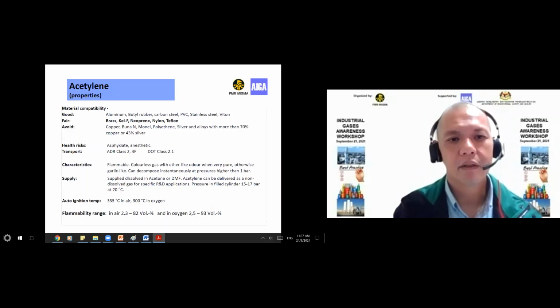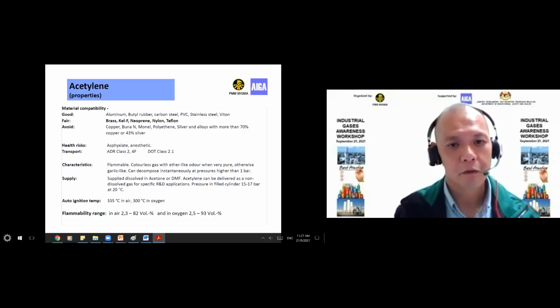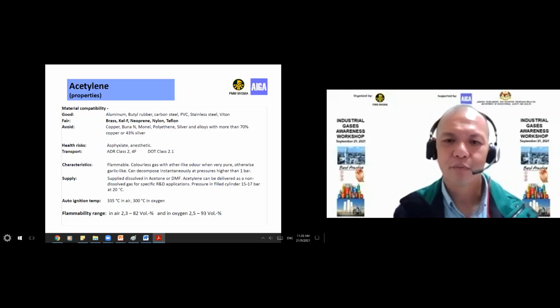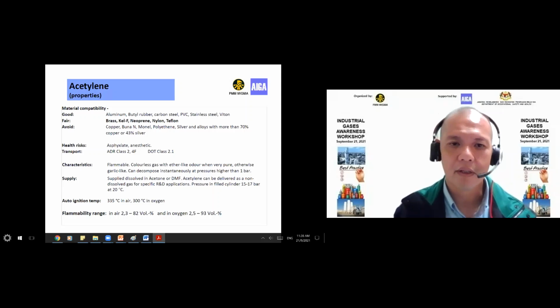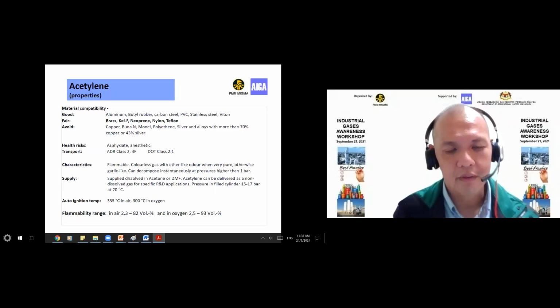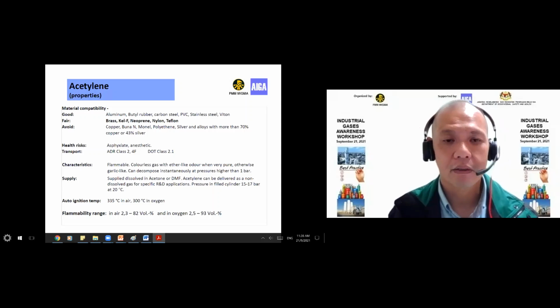Right, so here I want to share the material compatibility with acetylene. For acetylene, there are some good materials that are very compatible, like aluminium, rubber, carbon steel, PVC for lower pressure, stainless steel, and Viton. On average compatibility, we have brass, Kel-F, neoprene, nylon, and Teflon. There are also materials to be avoided, right? Do not use these materials with an acetylene system.